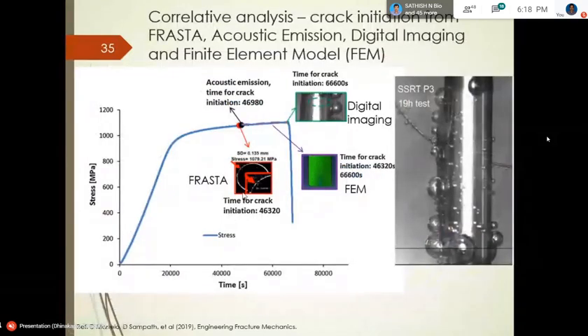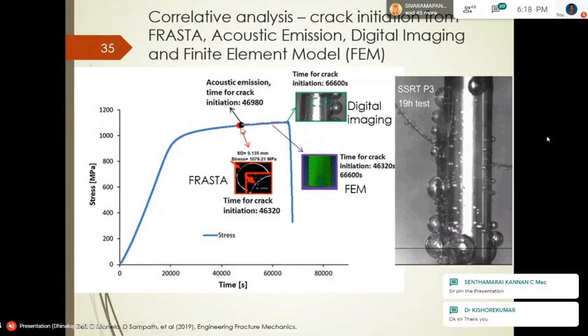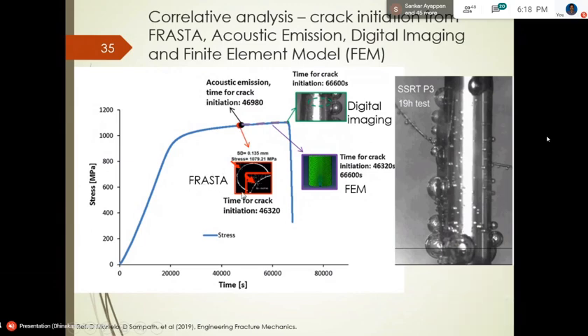And also we backed up using acoustic emission, which monitors the noise created in the process of cracking. So what happened was, this is the place where the crack initiated, when we found that using FRASTA. In acoustic emission, they also detected crack initiation noise at this point. So it is very well validating the findings of FRASTA.